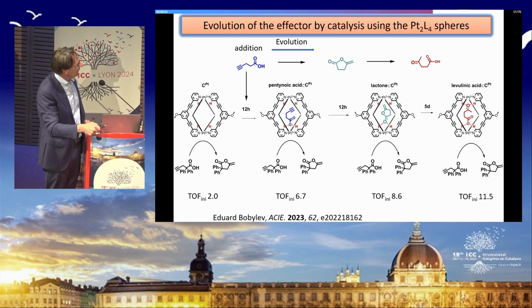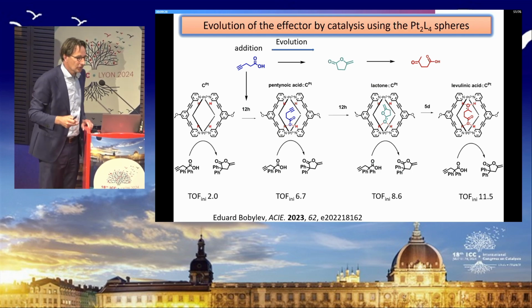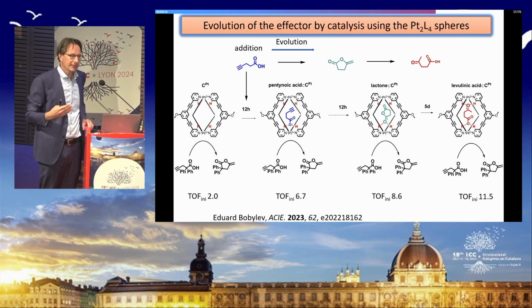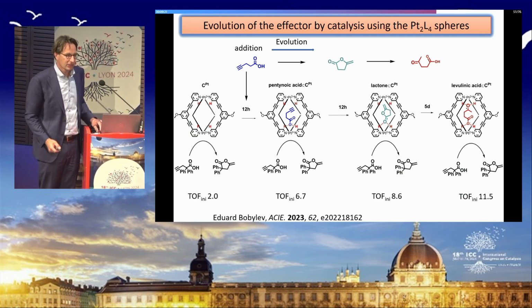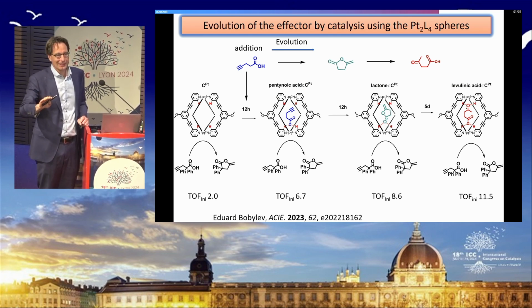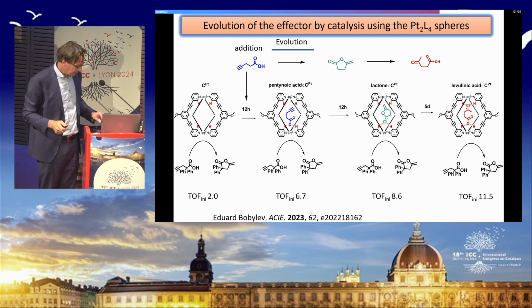And then over the course of 5 days, this cyclic compound is ring opened with water, forming this acid analog that is even a better effector, and adding again a substrate led to even higher reactivities. So this shows that we have a sort of auto-regulated reactivity of our catalyst. And although this is very fundamental and new, the vision here is that we would like to develop catalysts that respond to the environment, with the vision that if you look at biomass or waste mass, it contains a lot of components that may need a different catalytic activity.